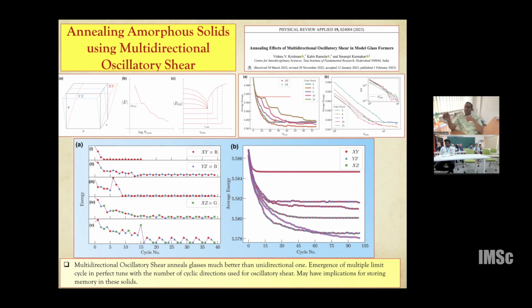And you can actually have various combinations of this. You can do X, Y, Z, and then repeat the same pattern, or you can have XY twice, and then YZ and XZ, and then repeat that pattern. Depending on what kind of pattern you choose, the steady state or the absorbing state that you get turns out to be very interesting. For example, in this panel, if you do unidirectional oscillatory shear on the XY plane, then you get a steady state which has only one energy scale. But if you do oscillatory shear in 3 directions, then you can reach a steady state which toggles through 3 energy states.